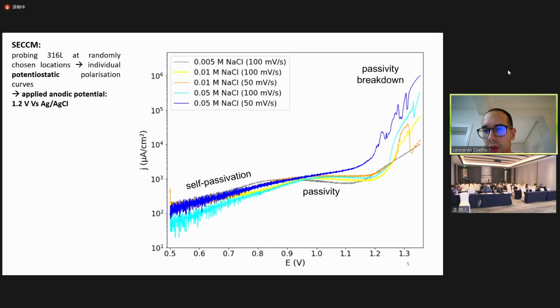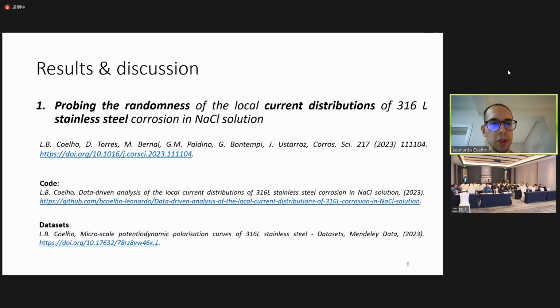And in the third study we will address, we chose a fixed applied potential equal to 1.2 volts. And our approach in this case was chronoamperometry. So fixed potential and the measure of current over time. And we chose this particular potential because it really is between two very important regions. We really are in between a transition zone: passivity of the metal, and then at a higher anodic potential, passivity breakdown.